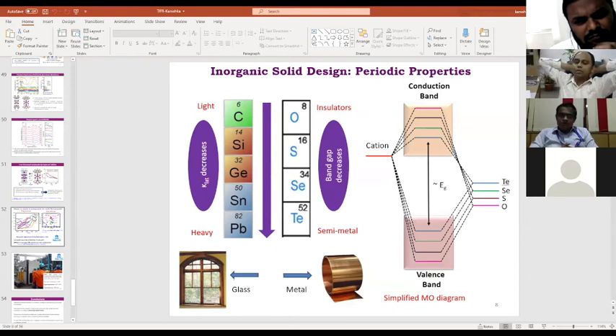Yeah, that is again a good question. Generally in physics departments you must have a cold press, right? Like you make a pellet. You give very little pressure, maybe a little bit of megapascal, and then make a hand-pressed pellet. Those are very low density pellets. If you have a crystal structure, you have a density, and those pellets will not even reach 80-85% density. So once you measure the electrical property, it may not be true all the time, because porosity and such artifacts may come.